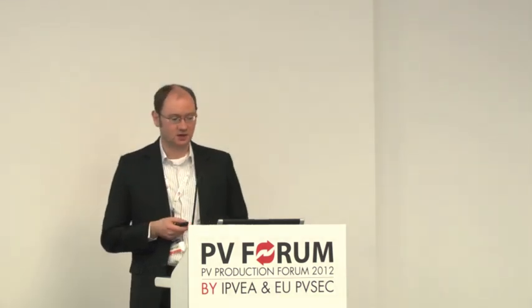Selective emitters are very much discussed and used by the industry today, and there are several processes available which are using different chemicals and gases. Selective emitters are used because low contact resistance is needed around the contact fingers, and this needs heavy doping, while the other areas in between the fingers require light doping in order to improve the surface passivation.